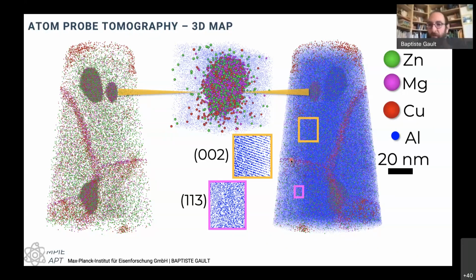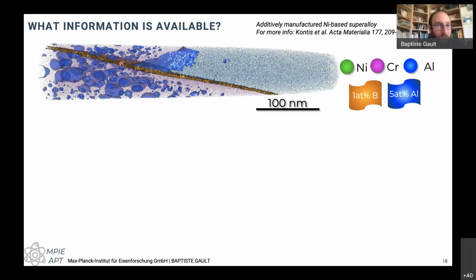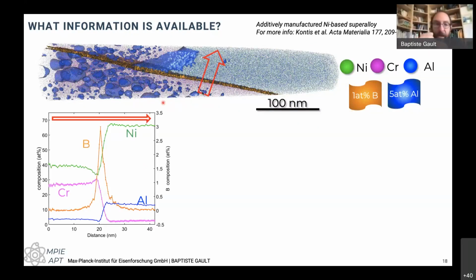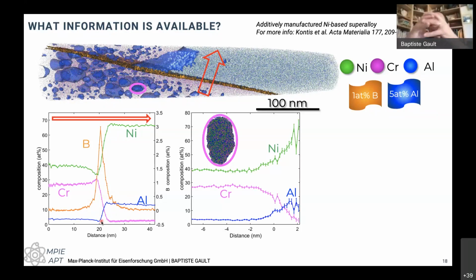But again, what sort of information can we get from this distribution of points? This is a nickel-based superalloy that was built by electron beam melting, one of these fancy 3D printing techniques. For example, I can do a composition profile through there, and count how many atoms of each species I have within a certain bin size or cylinder that I can define, all in 3 dimensions. I can see that there's a very strong boron segregation right at this grain boundary. Then I have the composition of gamma, which is this phase there that contains mostly chromium, so that's why it's a bit pinkish. And then I get into a very large primary gamma prime on the other side of the grain boundary, so it's nickel rich and aluminum rich. That's the sort of information we get. Also, I can isolate one of these particles and look at the way the concentration evolves as I go in and out of the precipitates. These are typical measurements that we would make.